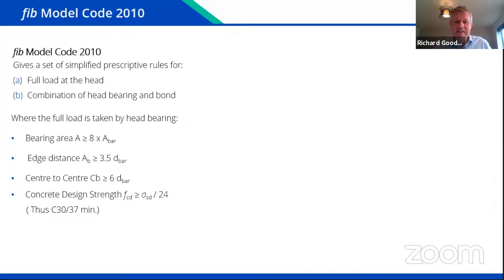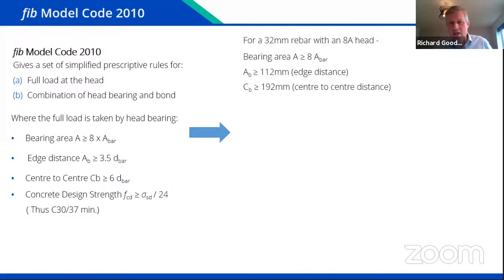And then it gives the center-to-center distance and edge distance spacing requirements as a function of the bar diameter, all for a minimum concrete strength. But if we were to put numbers to that, it means that for a 32 millimeter bar, we get an edge distance requirement of 112 millimeters. That's from the center of the bar to the edge of the concrete, and a center-to-center distance of 192 millimeters.